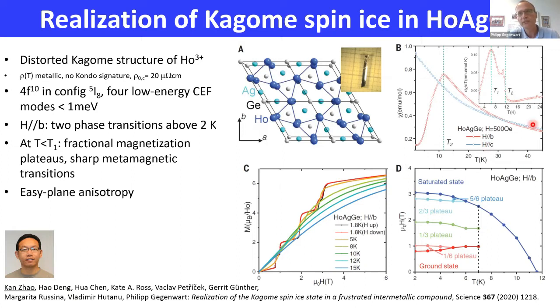So upon cooling, we see in the magnetic susceptibility several subsequent phase transitions, and in the magnetization curve measured at 1.8 Kelvin, this is the black and red data, we see multiple steps and fractionalized magnetization plateaus. As you see, the saturated state at low temperature has a magnetic moment of 6 μB, and we have a first pronounced plateau at 1/3 and a second pronounced plateau at 2/3, and there is also a smaller plateau at 1/6 and another plateau at 5/6. And these plateaus are separated by sharp metamagnetic transitions.